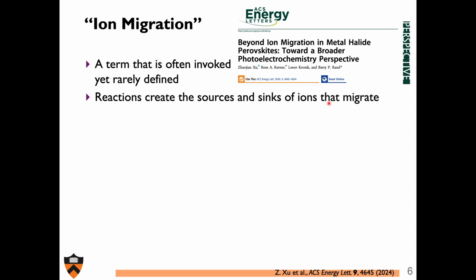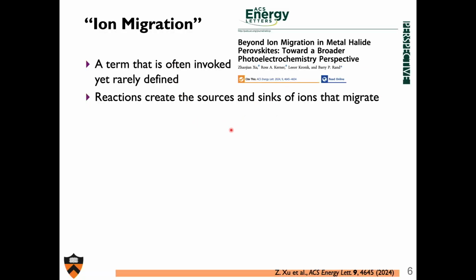What I'm going to talk to you mostly about today are less spontaneous, are non-spontaneous ones. These are ones that happen with the application of stress, either voltage bias or light bias. And we just published a couple of weeks ago this perspective in ACS Energy Letters. And what we're trying to do is go beyond ion migration. So ion migration is this often invoked term in the literature of perovskites, but it doesn't really get to the core and the heart of what has happened. Yes, matter moves, but what mediates the movement of matter, the movement of ions, is actually some creation somewhere and some annihilation somewhere else. And so these are usually electrochemical reactions. And so behind ion migration is some sort of electrochemical reaction, because they are the sources and the sinks of ions that end up migrating.